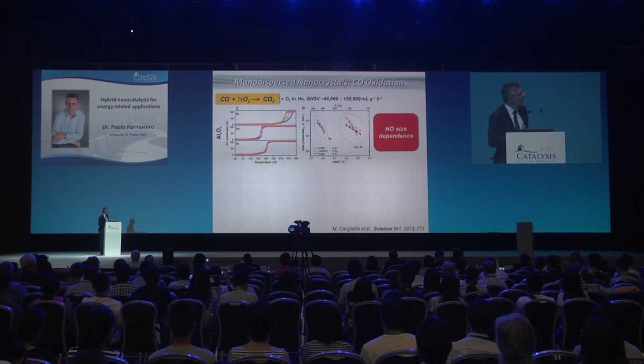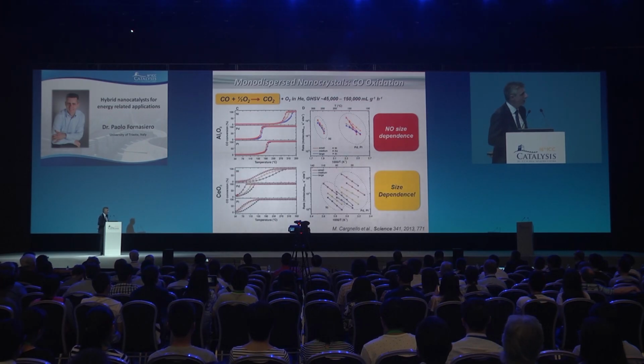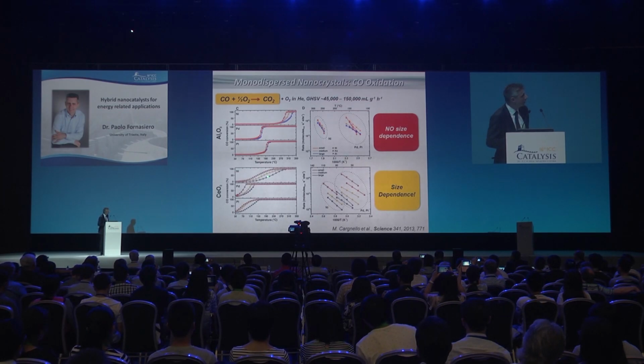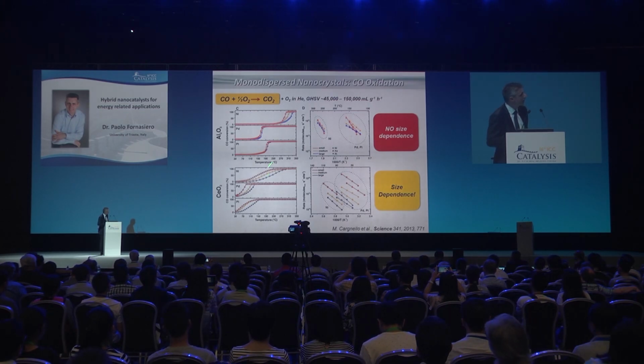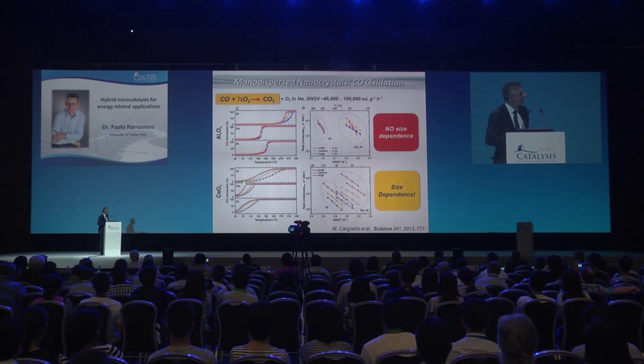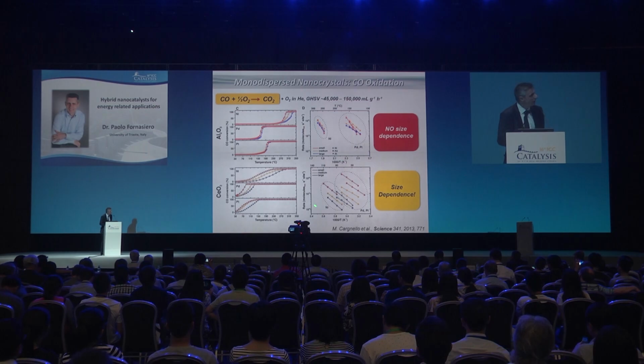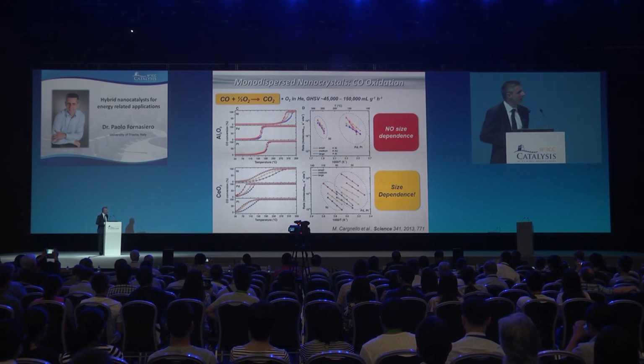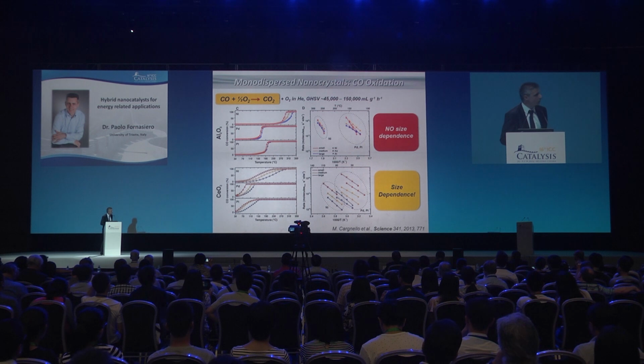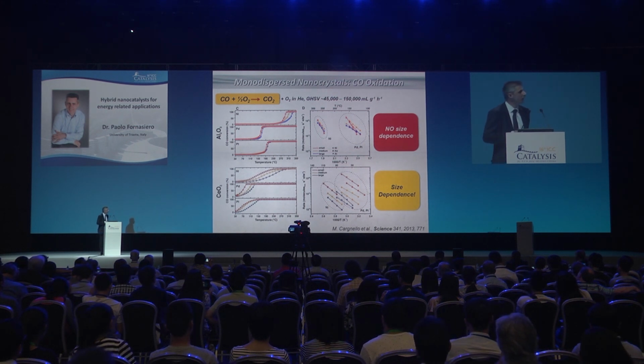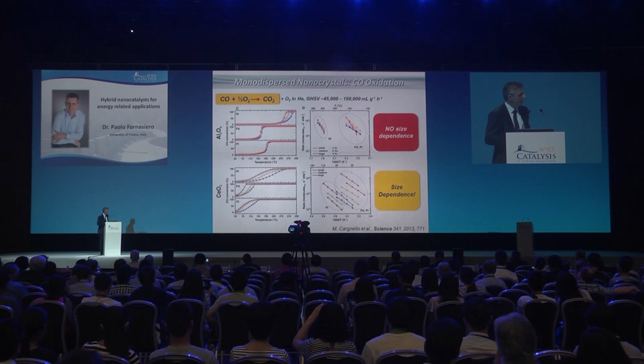You can see that on alumina, the nickel is less active than palladium and platinum, as expected, as is well known. And in the Arrhenius plot, you do not see a size dependence. Different is the case on cerium dioxide, where you can already appreciate the higher activity, the shift in the light-off temperature to lower temperature. Nickel is still less active than palladium and platinum, but in this case, you can observe that there is a size dependence, small nanoparticles being more active than medium and then large.